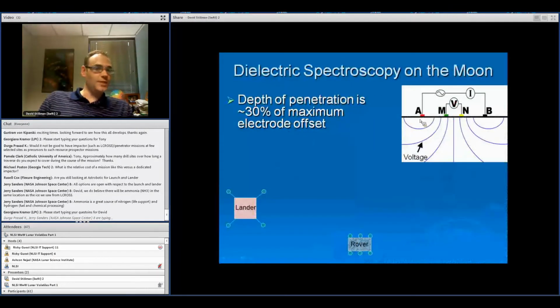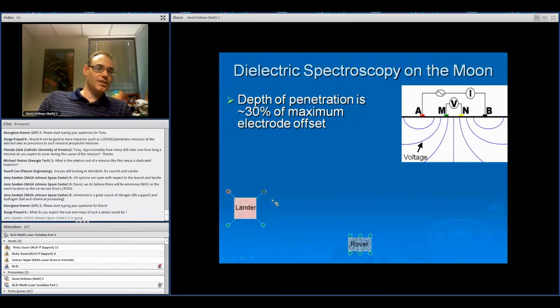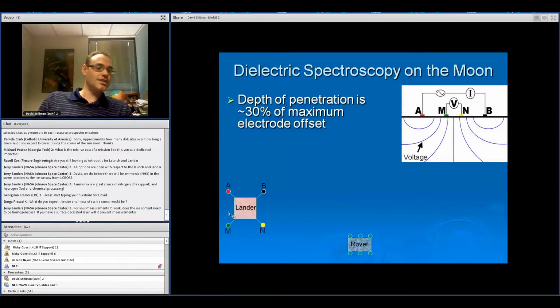So then, how do we actually do this on the moon? Some ideas. Our depth of penetration is about 30% of our maximum offset. So if A to B here was 10 meters, we'd be able to see 3 meters into the subsurface. And so what we could do is, if we just had a static lander, we could put electrodes on its landing legs and just detect the subsurface directly beneath the lander. Or we could put these on rover wheels and profile as that rover drove along.